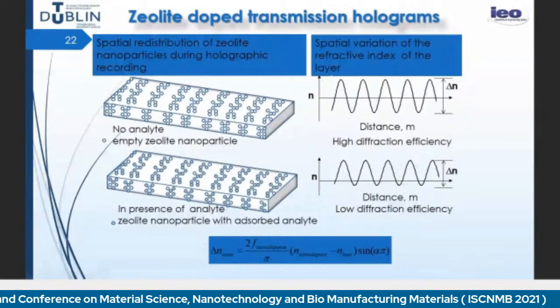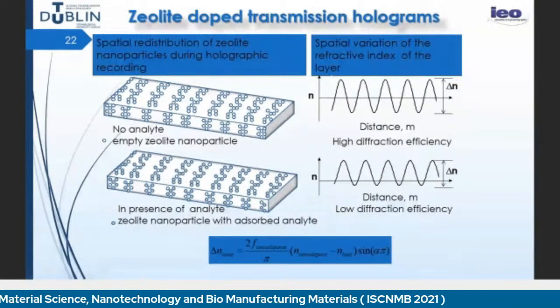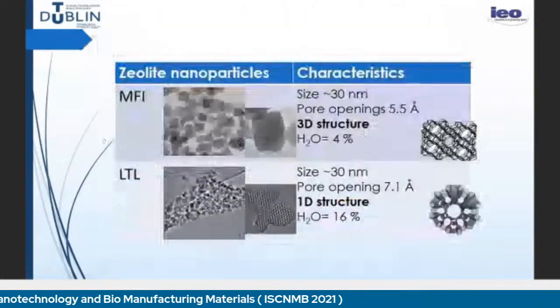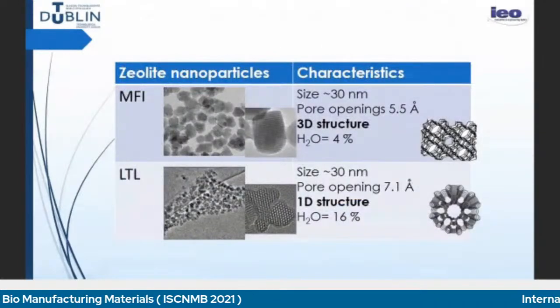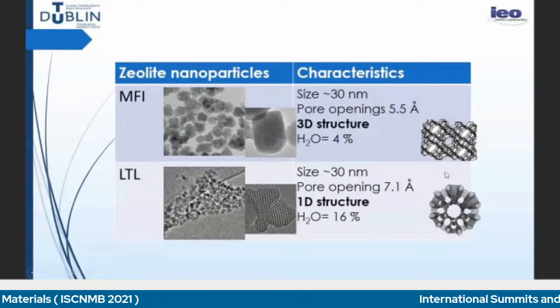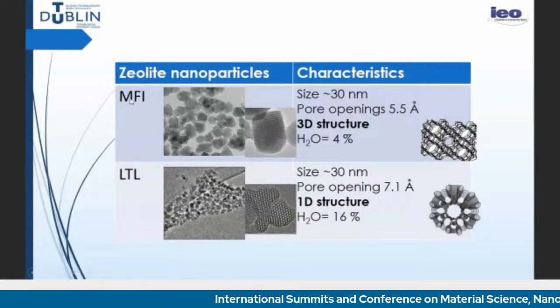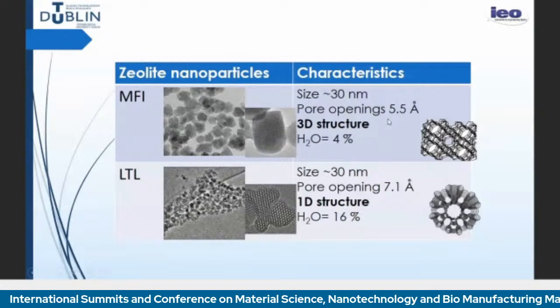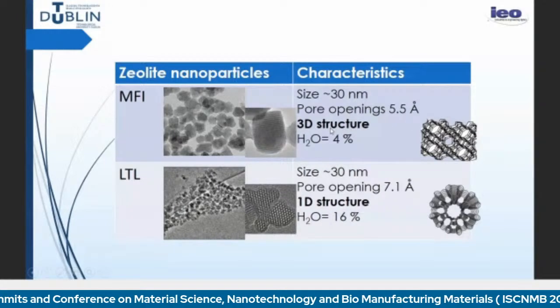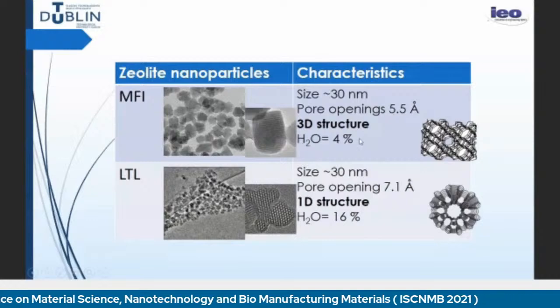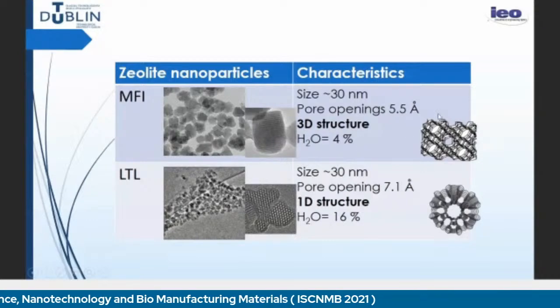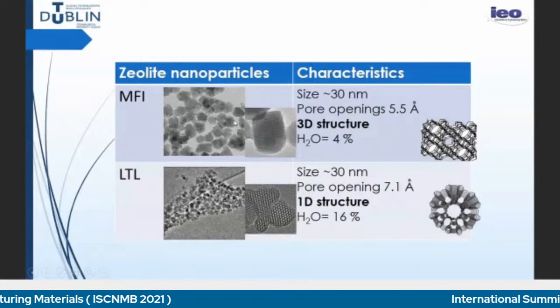And this is how we observe a change in the diffraction efficiency. Now I'm going to show you some results from MFI nanoparticles and LTL nanoparticles. Why did we choose those two nanoparticles? The first one are hydrophobic nanoparticles with very small pore openings, 5.5 angstroms, and they have very low water content. And we have studied them and we have seen that they remain empty, although they are added into the photopolymer before, of course, exposure to the analyte.